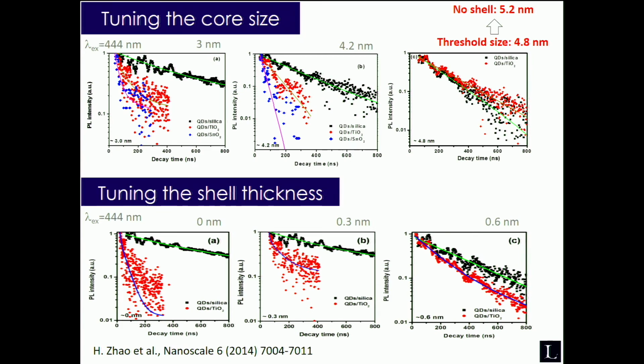What we did was to monitor the photoluminescence lifetime in different systems. We used silica particles, the black line, as a benchmarking system in which you have no electron transfer from the quantum dot to silica particles. So of course it has the longest lifetime.